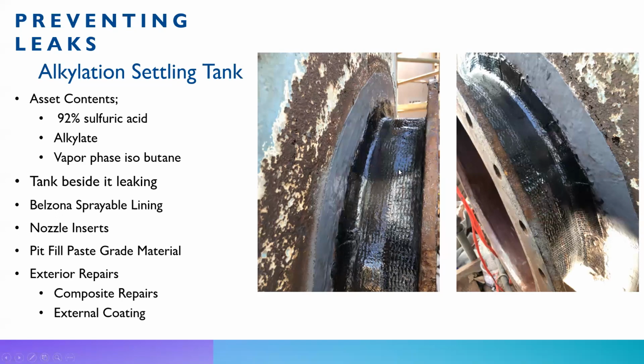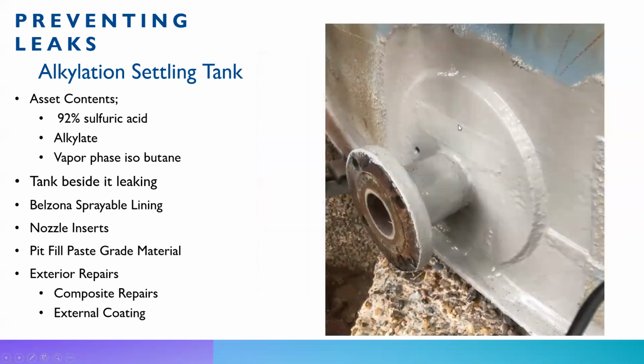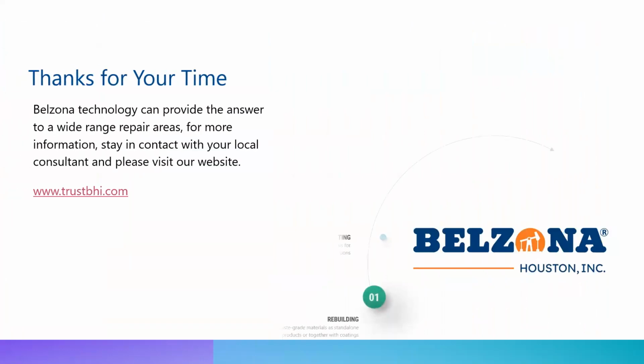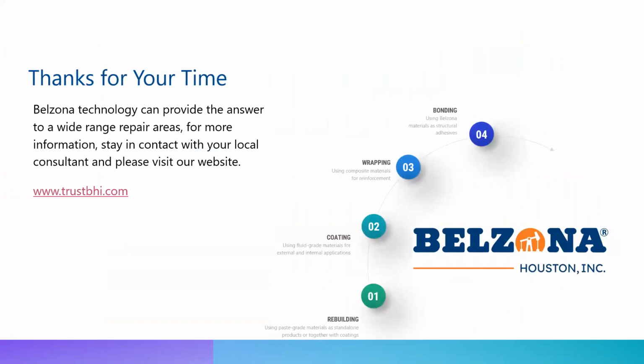There was actually a hole on the manway that they had a clamp over. So we installed a composite wrap over the manway as well. And we installed some composite wraps on some of the nozzles that were severely thin. And we coated a lot of localized corrosion on the exterior as well. So just a full bulletproof leak prevention and corrosion prevention system for that tank, starting from the inside all the way to the outside. And that was about 3 years ago, and everything's working great.